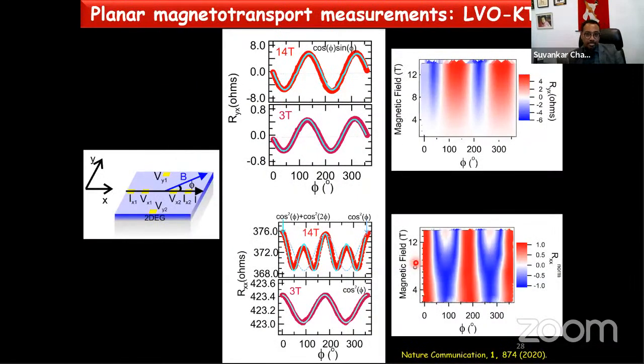So now we want to see what is known as the planar Hall effect and anisotropic magnetoresistance. So this is our magnetic transport measurement device geometry, where this is the 2DEG which is defining the XY plane. You send the current along the X direction and you rotate the magnetic field in the plane, and the direction between the magnetic field and the current is defined by angle phi. So what is the measurement geometry? You can measure this perpendicular voltage, which we call the planar Hall voltage, or you can measure along the direction of current, which we define as anisotropic magnetoresistance.